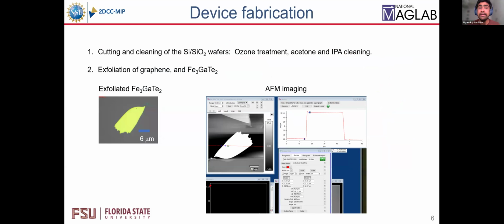For that, I exfoliated graphene on top of silicon dioxide wafers. The first step was to cut and clean the wafers. For that, I used ozone treatment, acetone, and IPA cleaning. This is a very basic cleaning procedure. And I exfoliated graphene and also Fe3GaTe2. So you can see the exfoliated Fe3GaTe2.